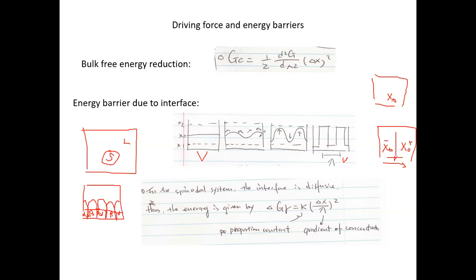Well, the thing that we do here is, how do you define an interface? If we say the interface comes from a sudden change the atom feels, we can consider that it is related to the concentration gradient, right? If you go from one phase and one region to the other region, you have some gradient which is associated with the drop of composition, which is delta X, and also associated with the distance over which this composition is going to drop. That is basically how we define the interface.